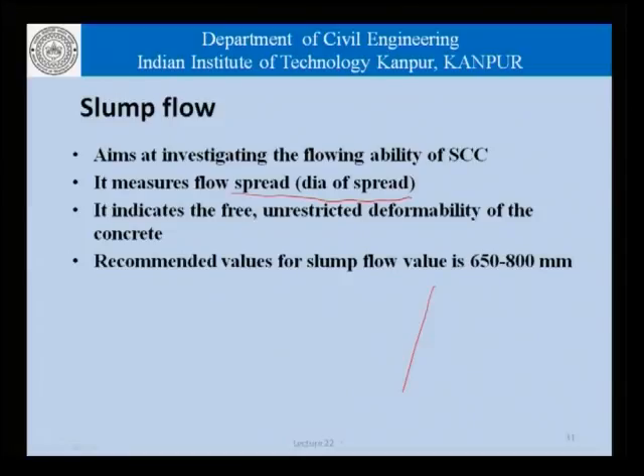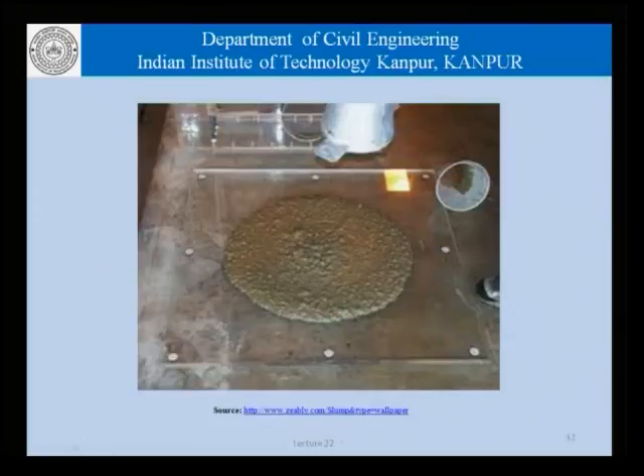What we must remember is that the standard slump cone measures 100 millimeters on the top, 200 millimeters here, and has a height of 300 millimeters. So, when we are talking of a slump flow of 650 to 800 millimeters, what we are really talking about is that this diameter here, which is what the concrete spreads into once the slump cone has been removed, this should be of the order of 650 to 800 millimeters or 600 to 850 millimeters. The original diameter here, as when it was contained in the slump cone, is about 200 millimeters. So, we are talking of a large spread of the concrete as the slump cone has been removed.